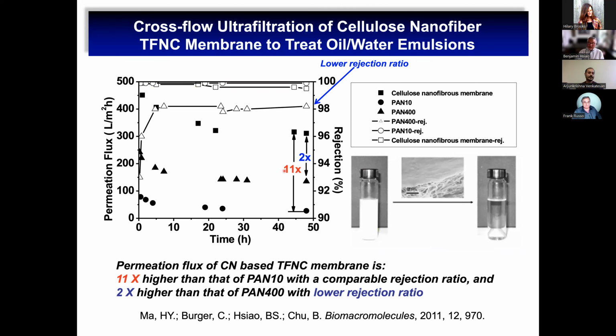Because the porosity of this membrane is very high, 80%, which is significantly higher than the typical sponge-like membranes made by the phase inversion process, the flux can usually be 1 order of magnitude higher. PAN10 and PAN400 are all commercial membranes. The rejection rate is about the same. So it's 11 times higher than this PAN-based membrane with a comparable rejection ratio. So this becomes a very high flux membrane.